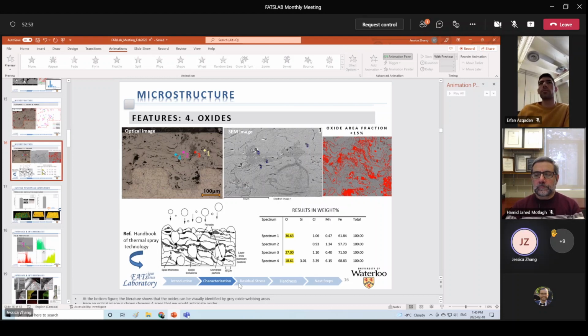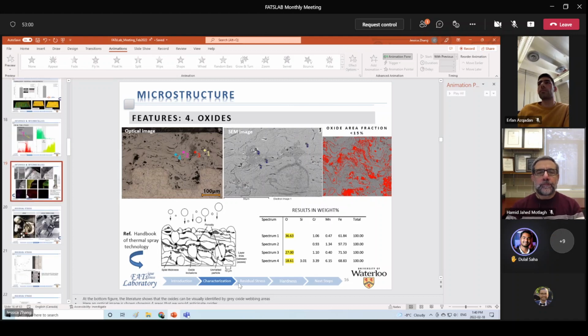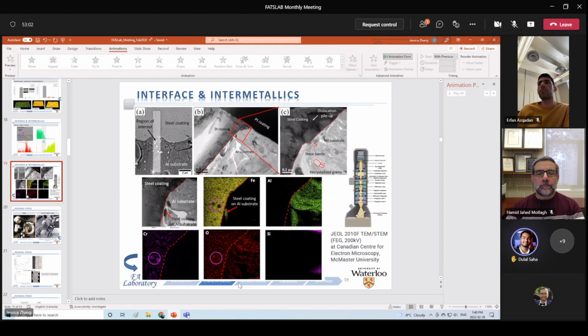Yeah, and just to add on to Andrew's question, there is some intermetallic present based on our discussion with our industry partner, because there is a nano layer of intermetallic present. They suspect maybe on the order of 5 nanometers. But when we initially started the TEM investigation, we didn't look into that nano level of the interface, but rather maybe instead of 5 nanometers, maybe 500 nanometers we looked into.